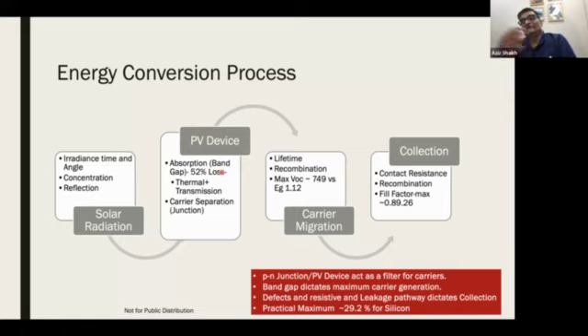And then you have to collect these carriers. So there is a contact resistance. There is again a recombination process during collection. As a result of all this, there is a calculation which was made, called the Shockley-Queisser limit. So the practical limit for silicon is 29.2%. That's all you can get after you do all this stuff.